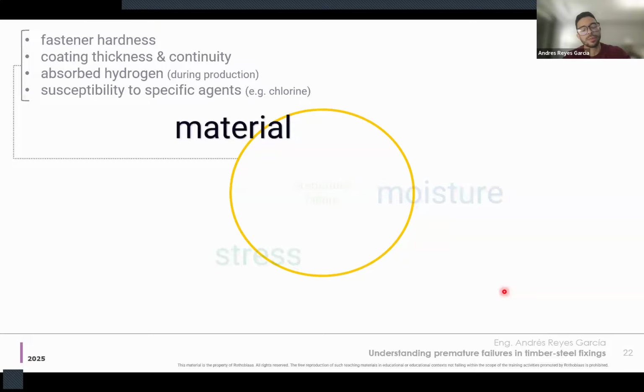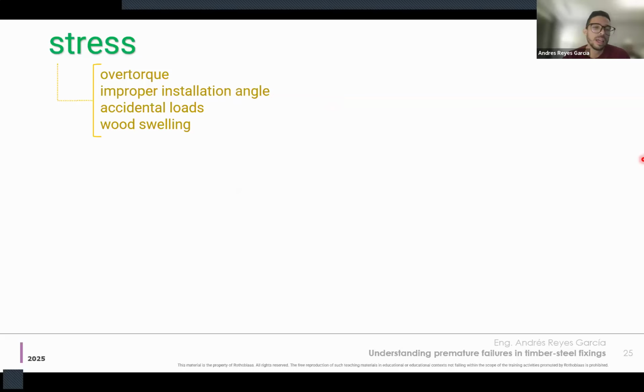Finally, material alone doesn't entail failure, because otherwise you would have broken screws in a box, and that doesn't happen. But the main material factors that influence failure are the fastener hardness, the coating thickness, the continuity of the coating, hydrogen absorbed during production, and susceptibility to specific agents. For example, stainless steels are very susceptible to chlorine. In those cases, finding alternative materials can also be a solution. These are more or less the factors from the material. Let's focus on the first one, the stressors.